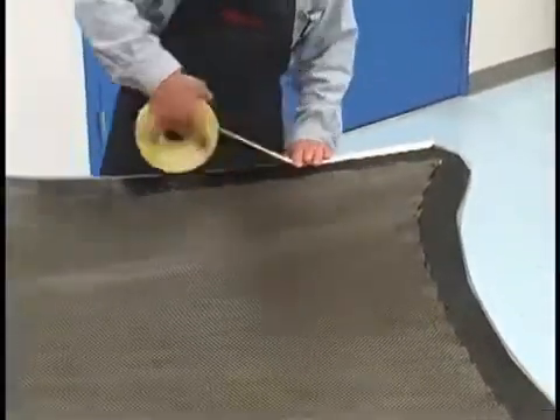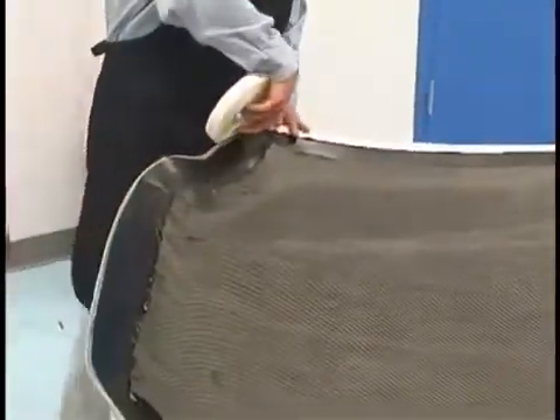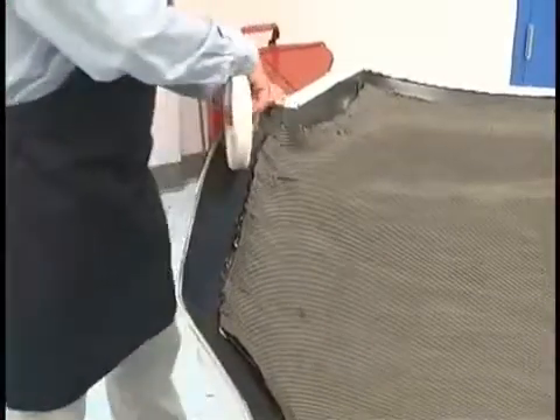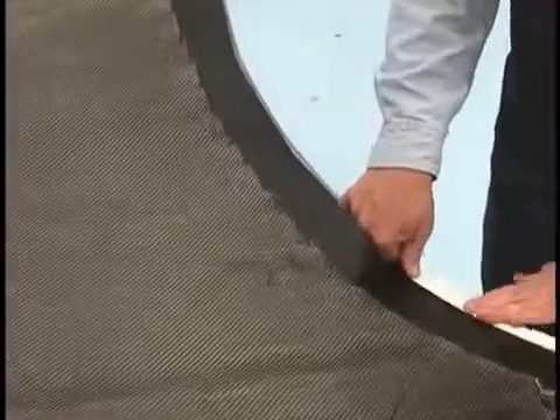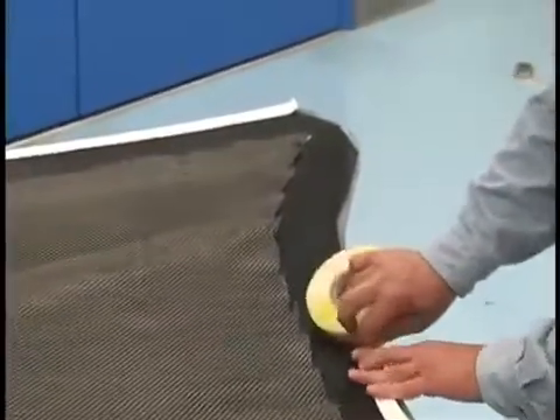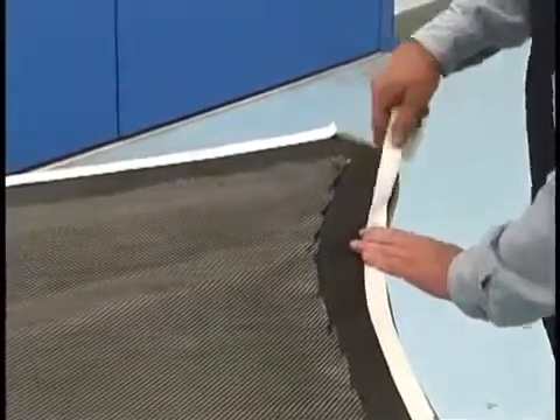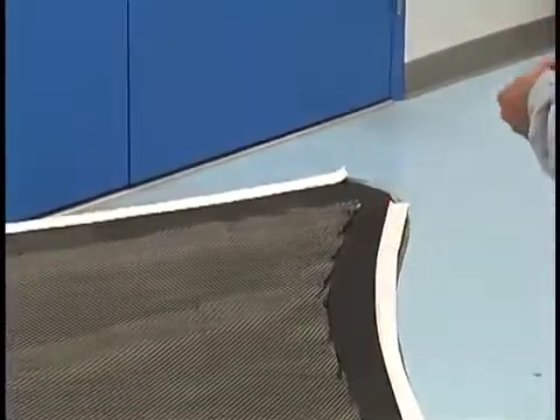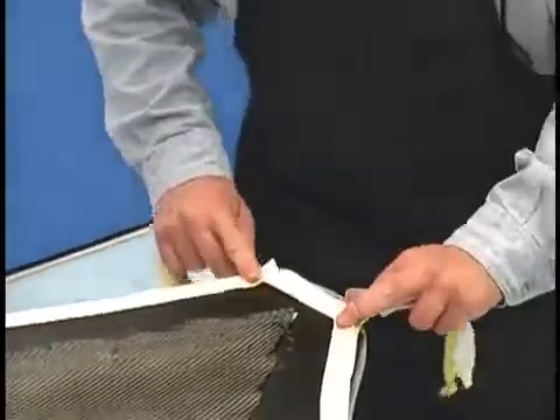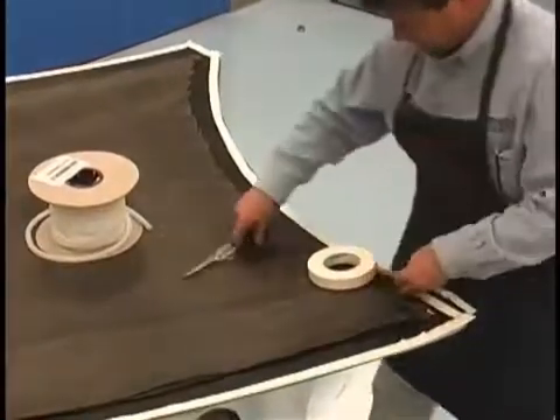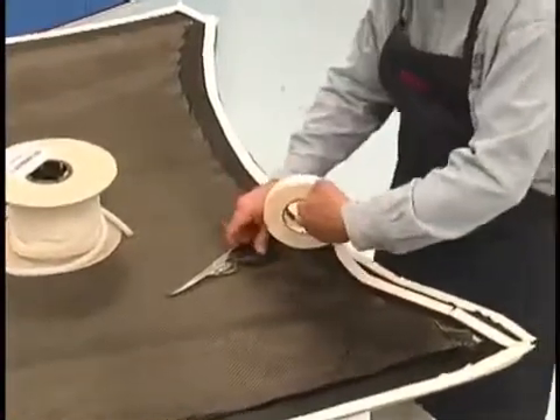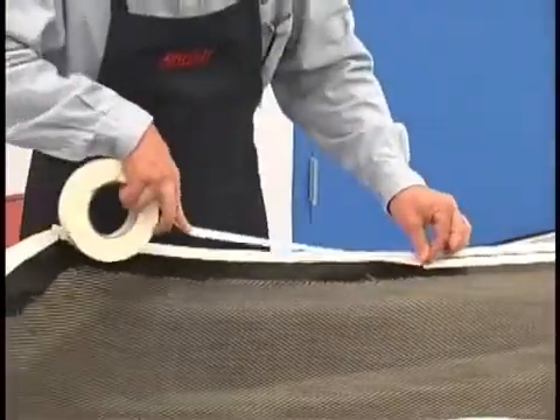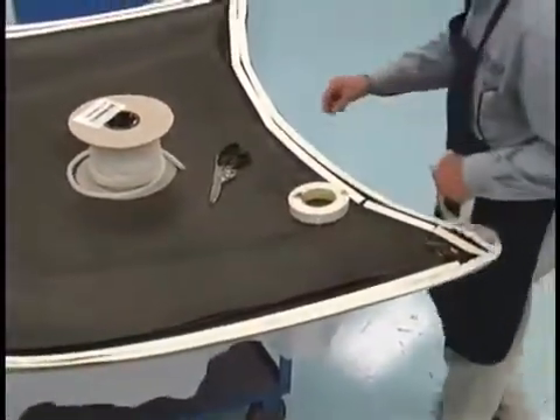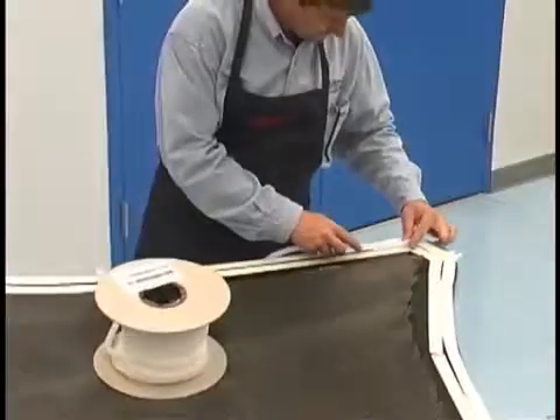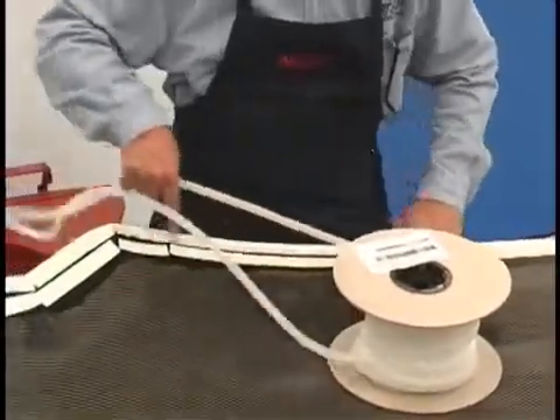Here we apply a vacuum bag sealant tape for providing a seal from the vacuum bag to the mold. In this case we are using AT200Y, one of our more economical sealant tapes. After that, we apply a double-sided tape such as Airhold 10 CBS. This allows us to later secure the polyethylene spiral wrap required for a peripheral vacuum manifold. The spiral wrap is then applied to the periphery of the mold just inside the sealant tape.